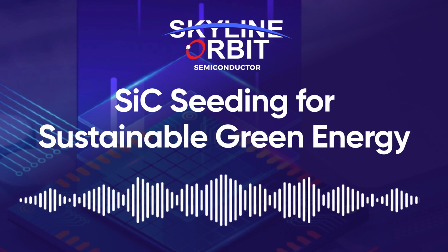Yeah. What can that thing do? What makes it special? So that Aixtron G10 SiC, that's like a state-of-the-art reactor that's specifically designed for growing these high-quality SiC epitaxial layers, and it lets you really fine-tune both the thickness and the doping. They usually use precursor gases like monosilane, that's SiH4, as the silicon source, and then propane or ethylene as the carbon source. And they carefully mix these with carrier gases like hydrogen or argon.